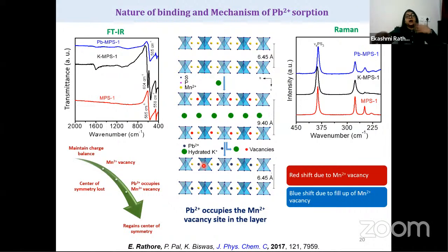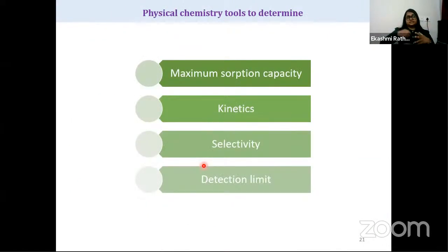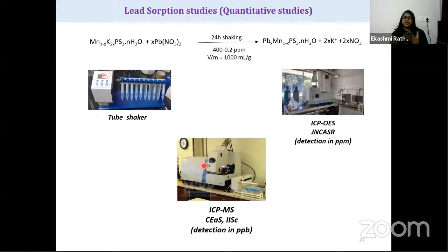Now let's see how we can do the quantitative analysis. I've used the physical chemistry tools to determine maximum sorption capacity, kinetics, selectivity, and detection limit. So how do we carry out this study? We use 10 milligrams of our sample, and we take 10 ml of the artificially prepared solutions in the range of 400 to 0.2 ppm.